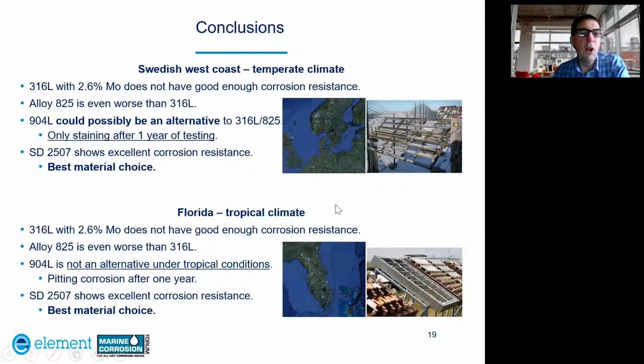So in the tropical climate, the 316L, unsurprisingly, did not have good enough corrosion resistance. And also the alloy 825 was even worse than the 316L. So the 904L did not provide an alternative under these tropical conditions, because it showed pitting after 1 year of exposure. So under these tropical climate conditions, the only choice of material would be the Super Duplex 25% chromium grade, which showed excellent corrosion resistance.